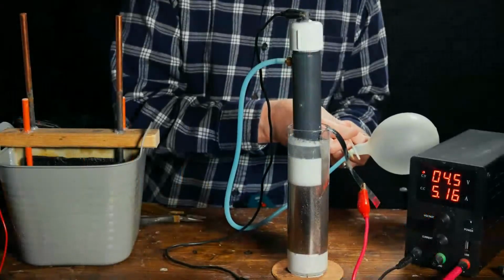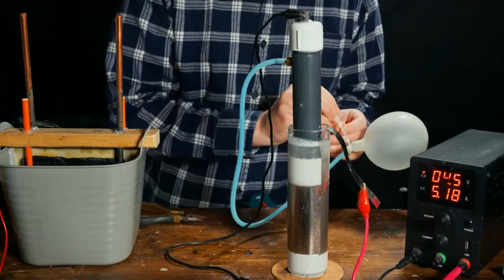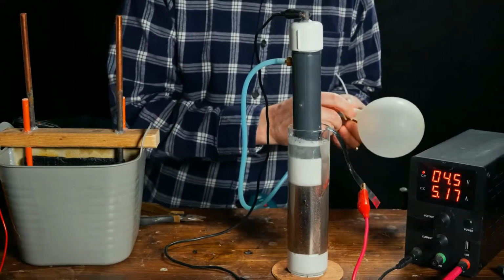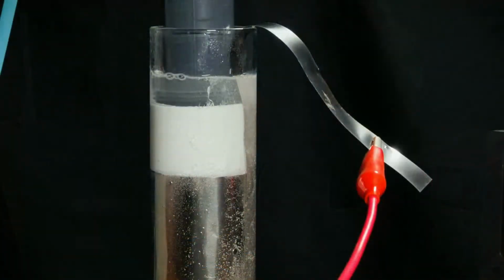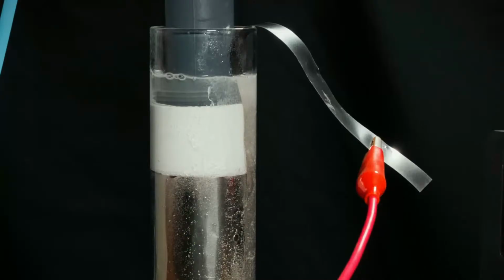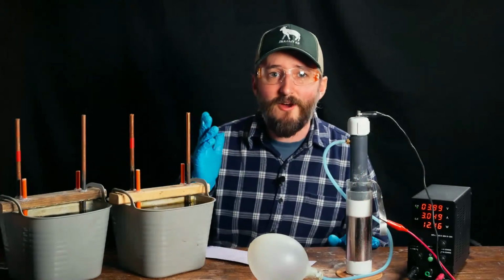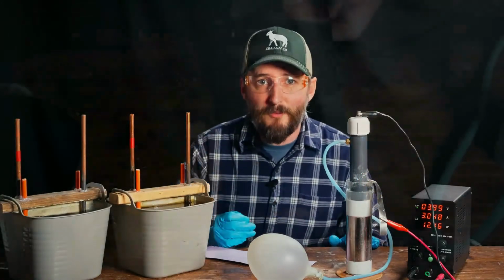I'll be using a solution of sodium hydroxide as my electrolyte, which is one of the rare things that's pretty tough on carbon when you pass a positive current through it. The carbon felt would dissolve fairly rapidly as the oxygen made in this process facilitates the hydroxide in converting the carbon into carbonates and other organic gunk that can clog up the membrane.